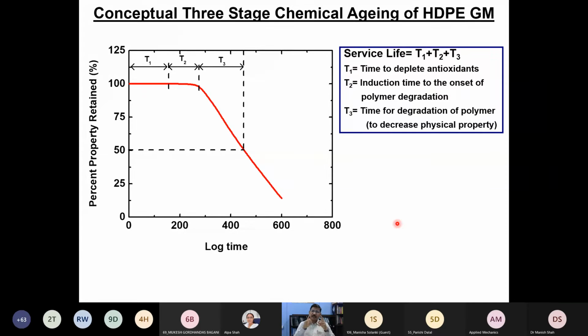Your service life has 3 components. One is T1, T2, T3, something like your life: childhood, middle age, and then the latter stage. Basically, T1 is the time to deplete the antioxidants. Initially, antioxidants are present in a significant portion in the geomembrane, and it depletes. But when the antioxidants in the geomembrane become 0, that doesn't mean that the geomembrane immediately lost its mechanical property, or lost its diffusive property, or lost its melt flow index, or lost maybe the crystallinity.